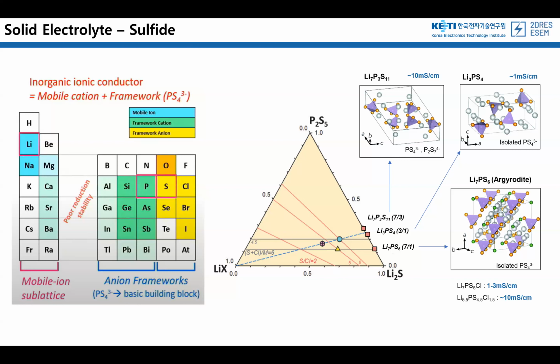Li7P3S11 has a higher ionic conductivity of 10 millisiemens per centimeter, but it is difficult to synthesize and has limitations of electrochemical instability. Li7PS6 is another type of solid electrolyte that is created by increasing the portion of Li2S, which is an argyrodite type solid electrolyte. This type of solid electrolyte allows for lithium migration due to the excess lithium in the structure. However, the ionic conductivity is still not large, and introducing chlorine by doping some of the sulfur can increase vacancies in the lithium sublattice and rapidly increase the ionic conductivity.